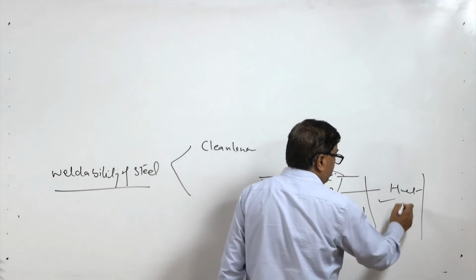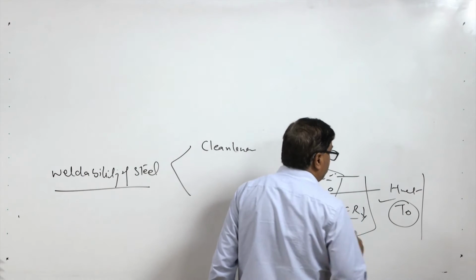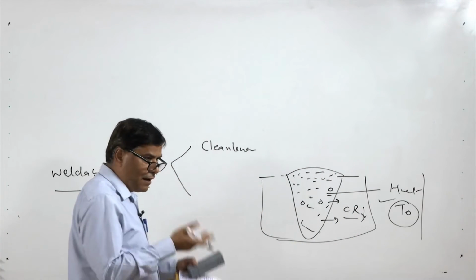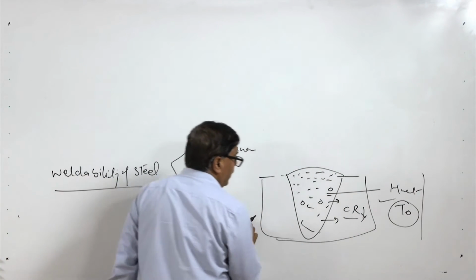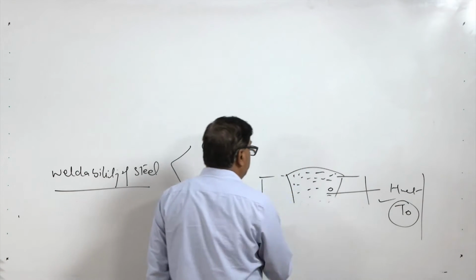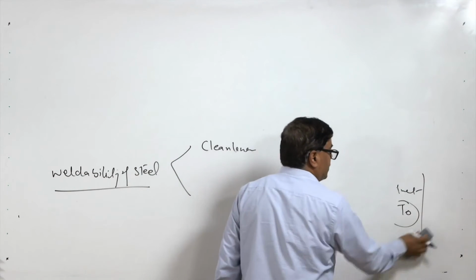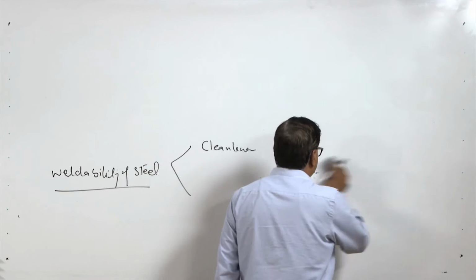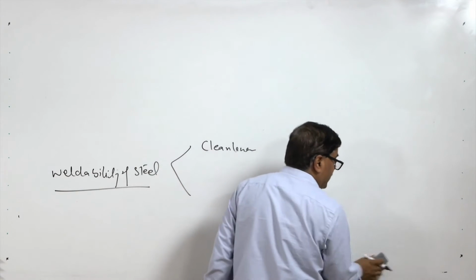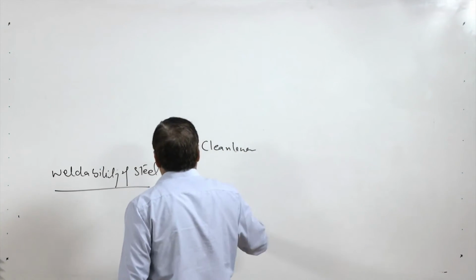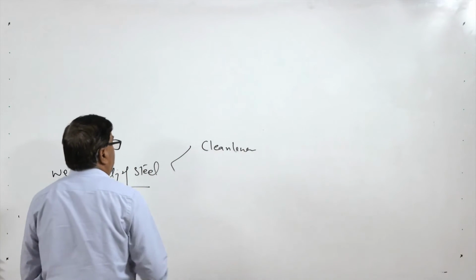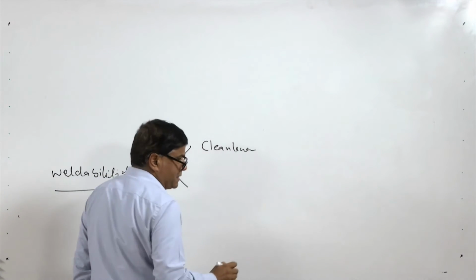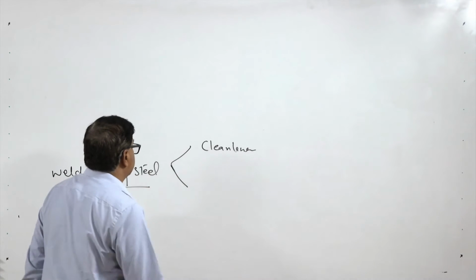A similar kind of effect is also offered by the initial plate temperature. If the initial plate temperature is high, then the cooling rate will be low, and the longer solidification time due to the low cooling rate will result in a cleaner weld as compared to cases where the solidification rate is high. So, solidification rate in general affects the inclusion entrapment tendency.